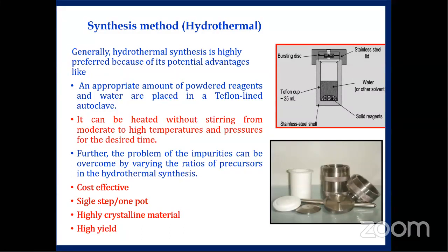Generally, hydrothermal synthesis is preferred because of its potential advantages. It is cost effective, and also a single step method, highly crystalline. The hydrothermal method looks like a pressure cooker. This is a Teflon lined autoclave. The precursor solution is taken in the Teflon lined autoclave and kept at a set temperature. You can change the concentration of precursors to get different size and shape, and you can also change the temperature. So by changing the temperature you can tune the size and shape also. By this method, many graphene nanocomposites and binary compounds are prepared with highly crystalline nature of this nanostructure material.